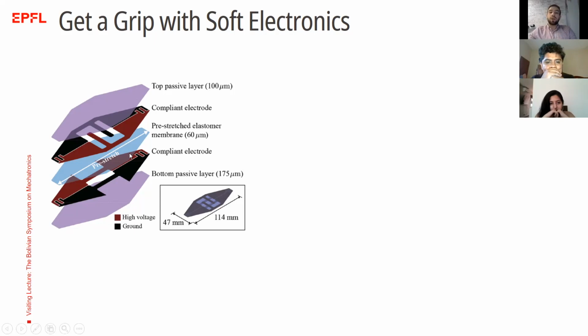And then a pre-stretched dielectric layer. So what you have in the end, in the middle, is a sandwich structure where you have two electrodes and the dielectric layer in between them. That's basically a capacitor. When we apply high voltage to both compliant electrodes, they try to squeeze the dielectric layer between them due to the Maxwell pressure. Due to that, we are able to change the bending angle of the actuator from the bent state to the straight state.